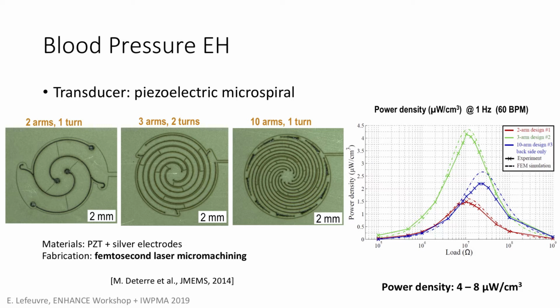So this is made in bulk PZT, but it's micro machined by a femtosecond laser. So it's a very, very nice tool, but very expensive. It takes a long time to fabricate. But the thickness of the PZT is 300 microns, so it's a bit thick. It's a bimorph. And the width of the openings made by the laser are only in the range of 20 micron, so it's quite good.